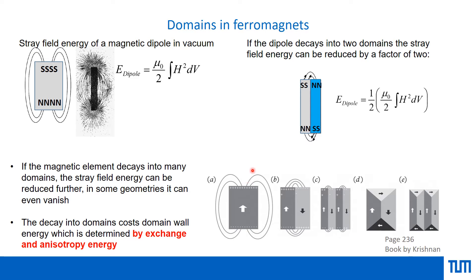To minimize energy, the system goes into domains. Shown for bar magnets, if you have two magnets next to each other in opposite directions, the stray fields are now denoted with very small lines, meaning the stray fields and dipolar energy already become half by dividing into two. Similarly, you can divide a magnet into two domains with magnetization pointing up and down, minimizing stray fields and energy.